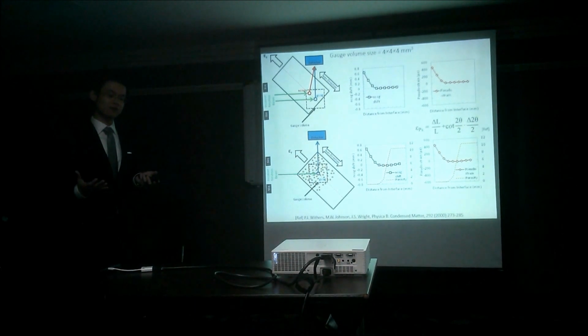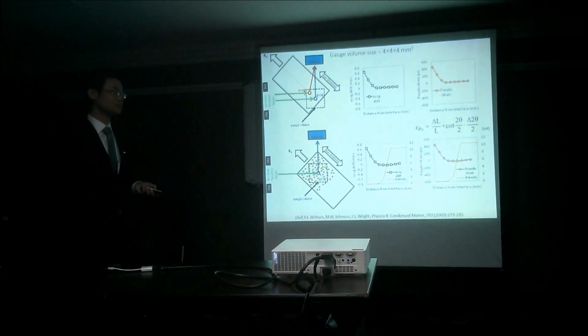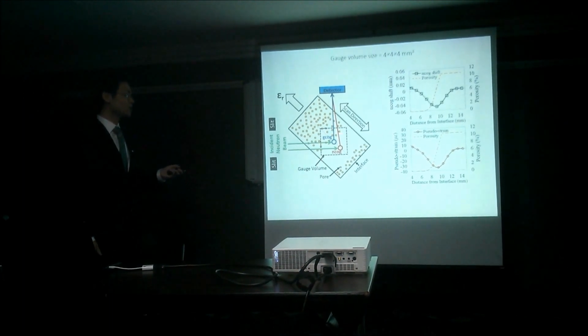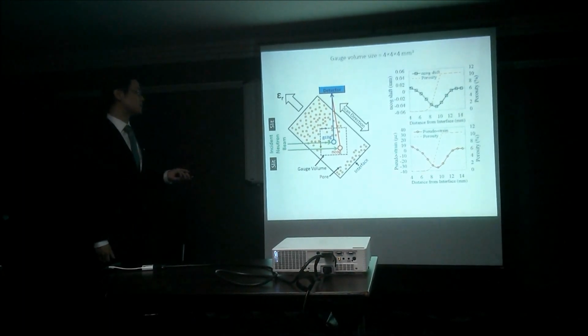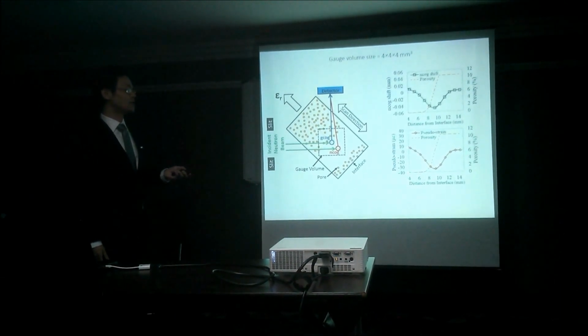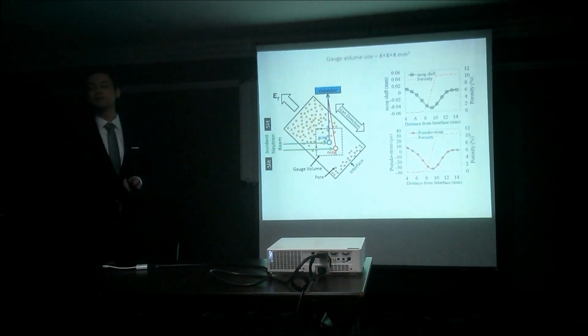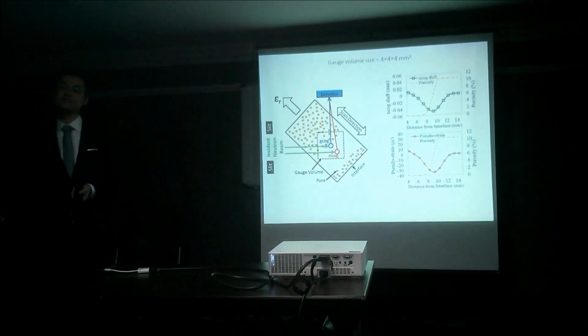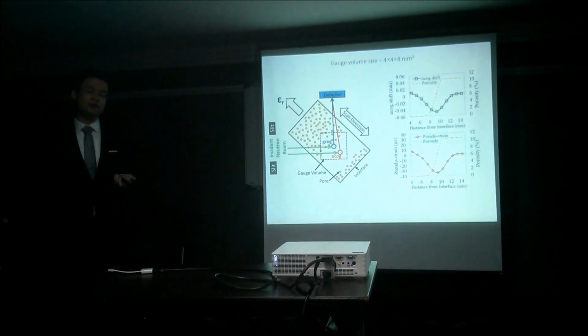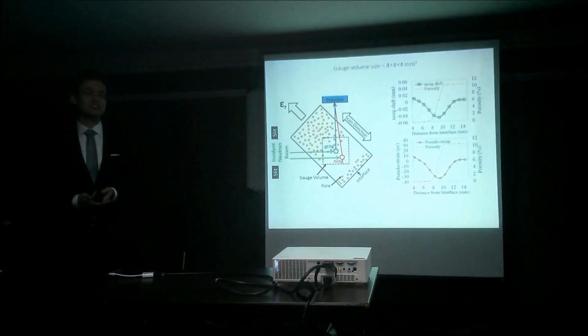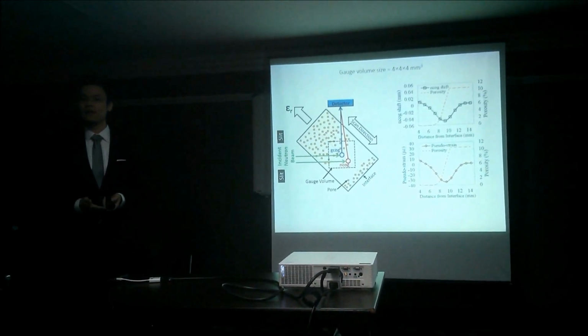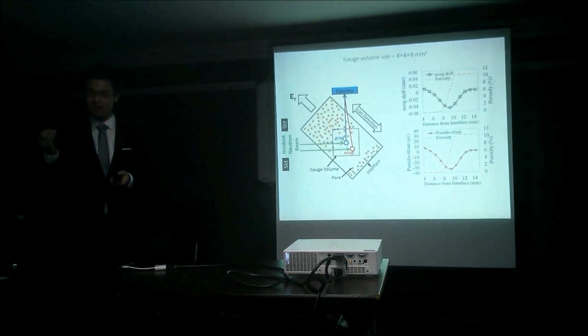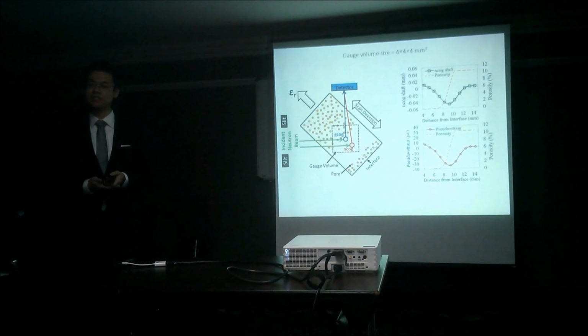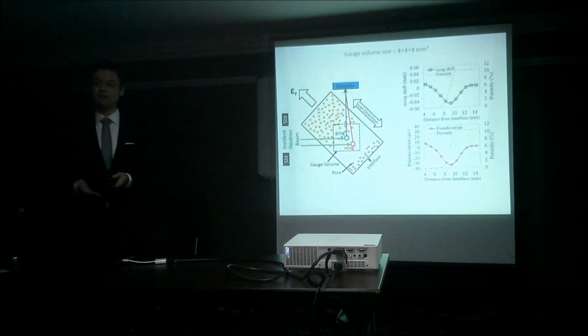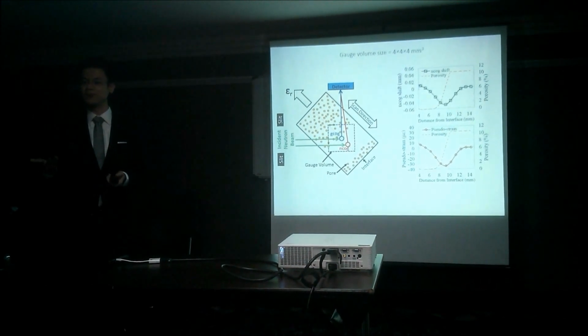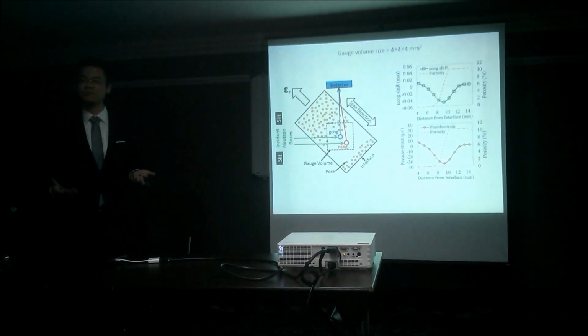Now, what if we just considered scanning inside our sample? In our case, we estimated a shift in the neutron center of gravity that led to a maximum pseudo-strain of about 35 microstrain, which is about 1/5 of our neutron diffraction measurement uncertainty. For other components with much more significant porosity, and in a case where the pore sizes are large and the gauge volume is small, this should definitely be considered and taken into account. And with the recent ISIS development for tomography-driven equipment and technology, I think this could be achieved relatively easily.